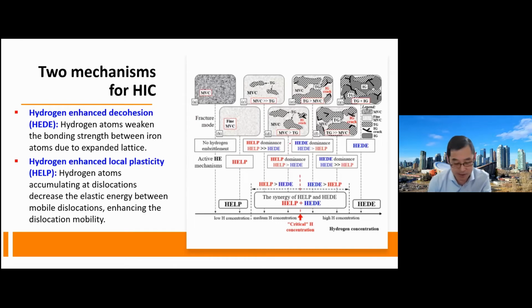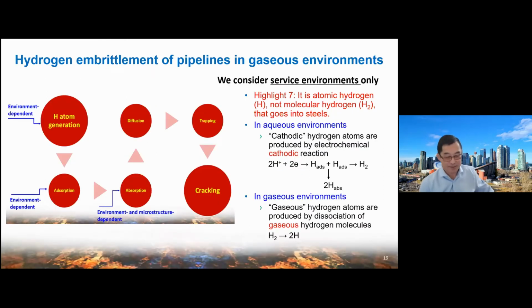I do not want to give too much detail about the two mechanisms. Use the graph on the right side; it also tells us whether HEDE or HELP applies actually depends on hydrogen concentration. Low hydrogen concentration usually gives the HELP mechanism, where hydrogen makes the steel soft. But if you have too much hydrogen in the steel, that's the HEDE mechanism, which makes the steel harder and can lead to brittle fracture. I will quickly skip these slides and go to the next one because I have so many slides in today's talk.